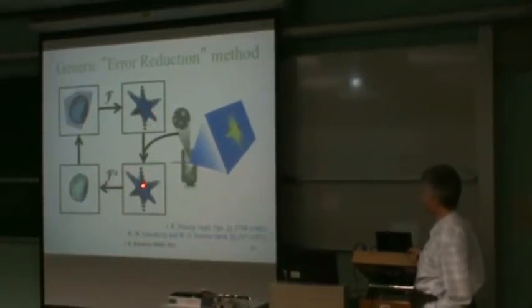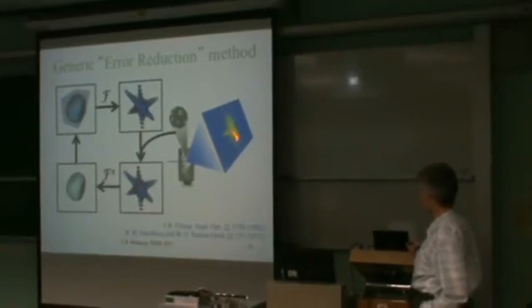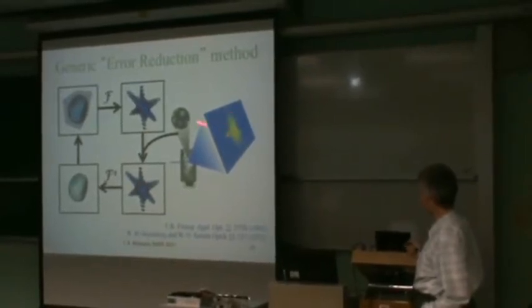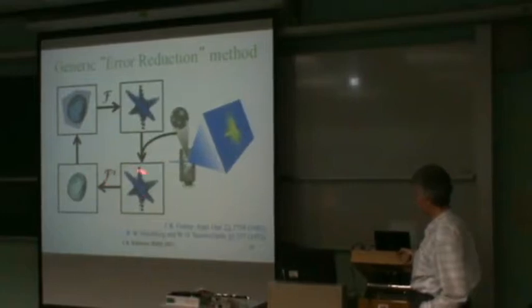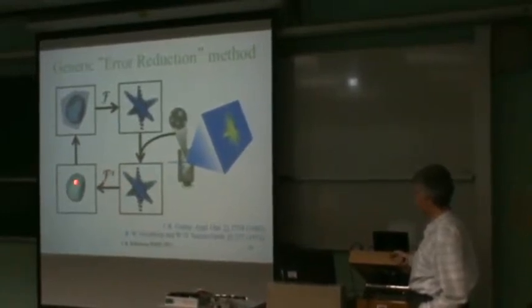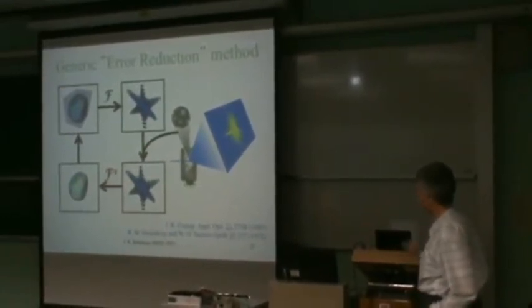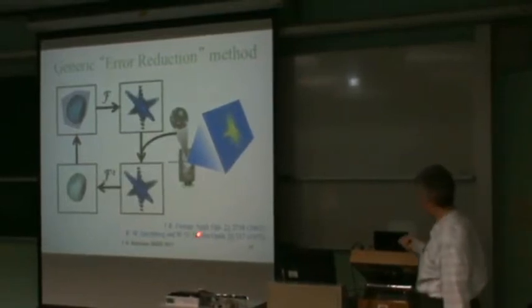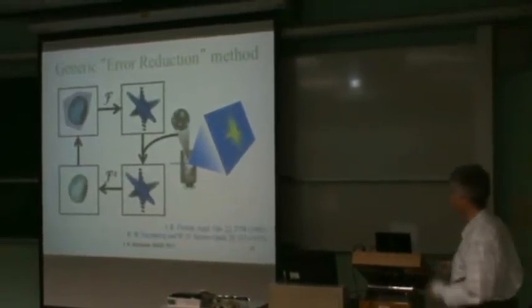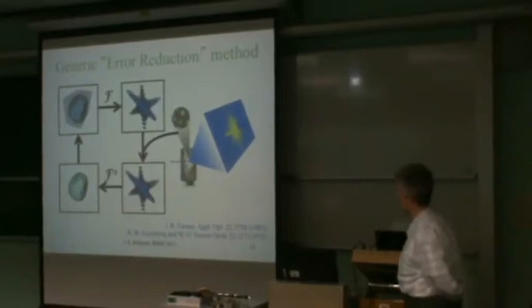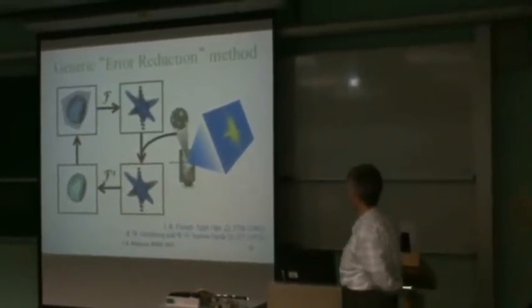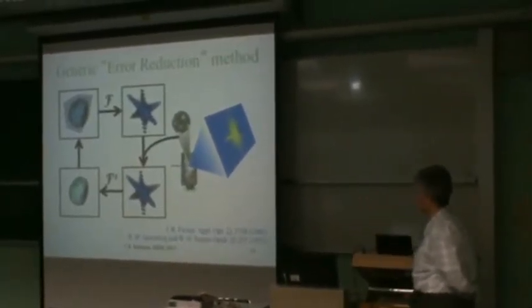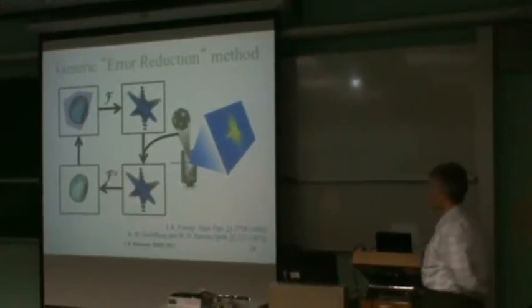You overwrite the amplitude with the measurement that comes from your instrument. You keep the phase, and then come back to real space again, and then go around in a circle. And with a few tricks invented by these authors here, you can get quite an efficient algorithm. And in fact, we trust this completely now, so we get quite good results.